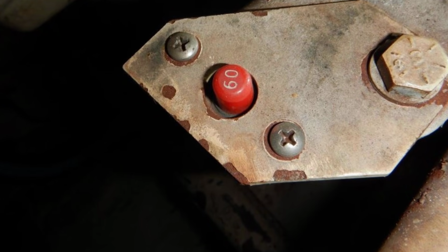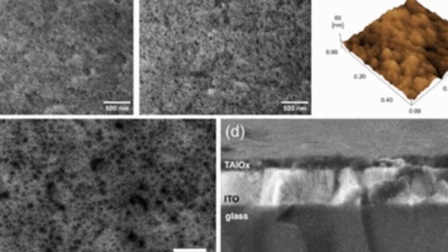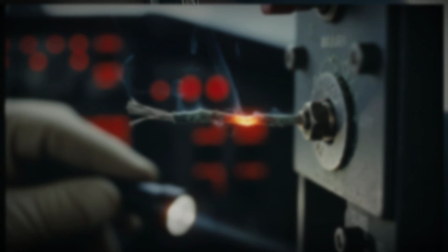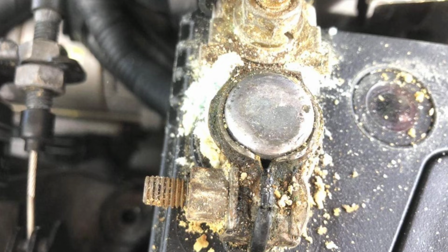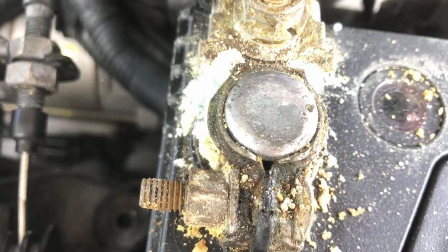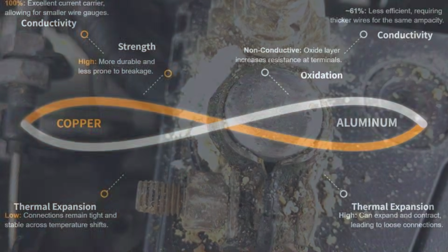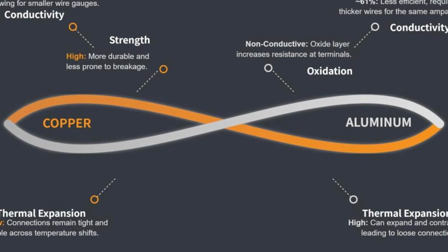This oxide layer increases resistance at the connection point. Even a thickness of 20 nanometers can block current, forcing electricity to squeeze through tiny spots where the oxide has cracked. Each time the current jumps, it heats the metal, and the oxide grows faster. The cycle feeds on itself.